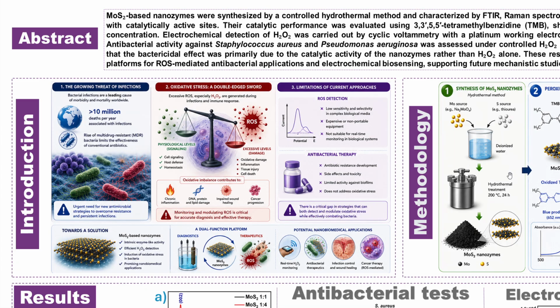In particular, molybdenum disulfide is very interesting because its physicochemical properties can be tuned by controlling the structure, morphology, and defect density. In this study, we focus on the peroxidase-like activity. This catalytic activity can promote the conversion of hydrogen peroxide into highly reactive oxygen species. These species can interact with the bacterial cells, producing oxidative damage to the membrane and other cellular components.